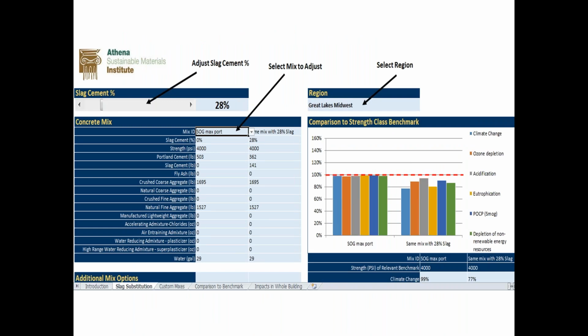On this tab, we are going to be able to adjust the amount of slag by just looking at this column up here where you're seeing the slag cement up on the top and it says adjustable percentages. We can raise or lower the amount of slag, and then we can look at that graph that's next door to it on the right hand side and see, compared to the benchmark that we need to use for this project, are we getting lower or is it going to be higher? And that way you can use that to see, okay, what's the minimum amount of slag I need? Or is there a way that I can improve and increase the amounts of slag?